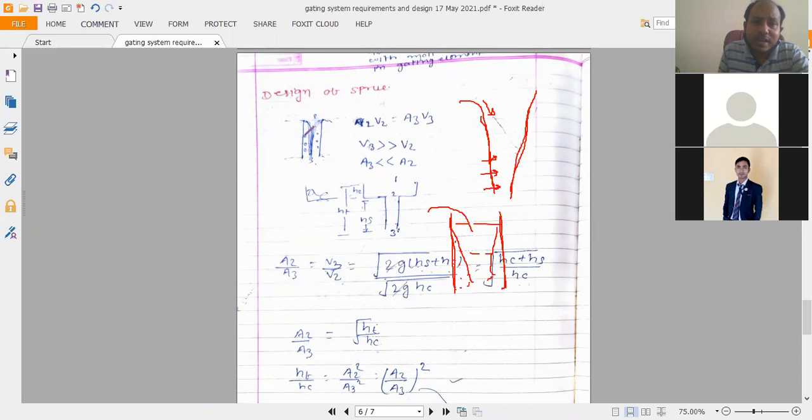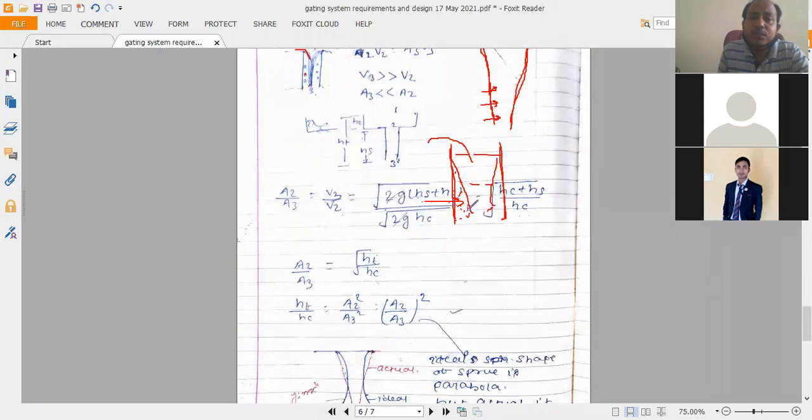Look at that. If we pour the molten metal into a cylindrical sprue, there is some portion at the bottom where the molten metal will not be kept or poured properly. In this part, air will enter and dross formation will occur, which restricts the flow of the molten metal to the other elements.